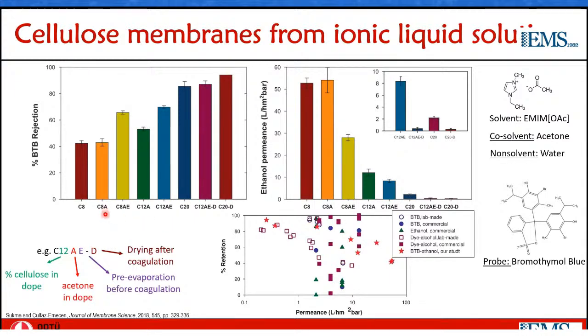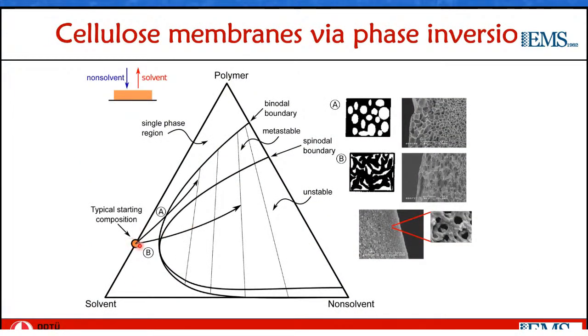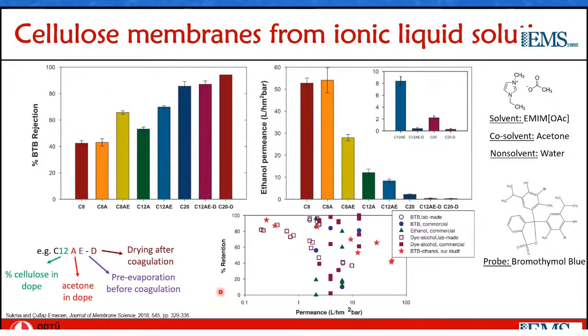Same thing occurs when we apply an evaporation step for acetone containing solution, which actually boils down to the same thing, where we increase the polymer concentration before entering the coagulation bath. And this is actually something that's common with phase inversion. If I just go back, when the composition path enters the two-phase region from a high polymer concentration, along a tie line, there's phase separation into more of a polymer-rich phase and less of a polymer-lean phase, which eventually makes a denser polymer structure. And a drying post-treatment, if you compare this and these two, also increases the rejection to the probe molecule by means of pore collapse.